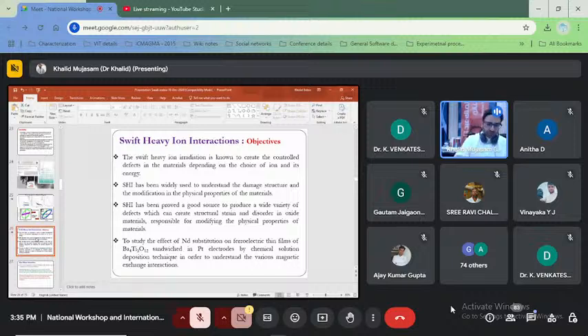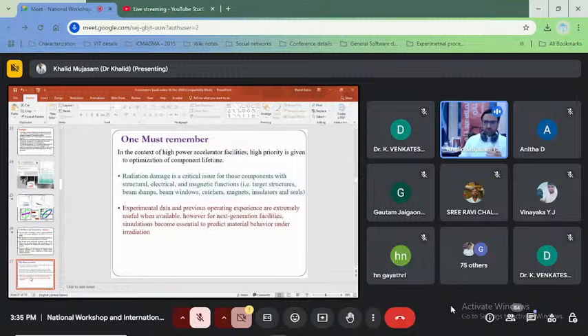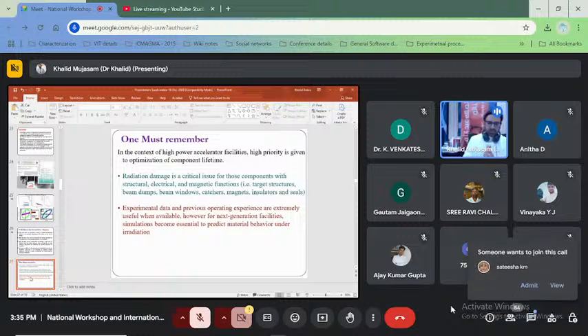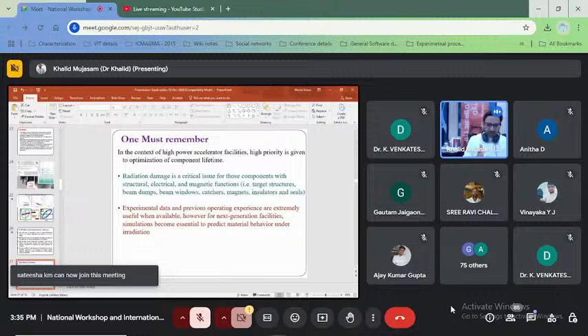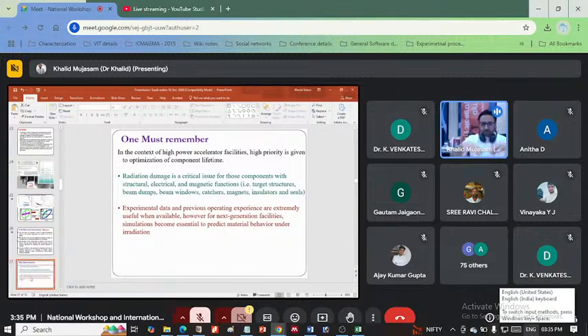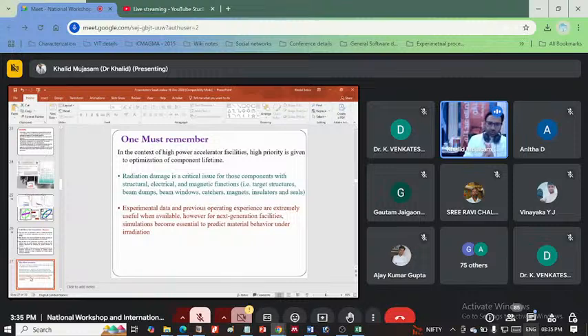That is ion beam implantation. In ion beam implantation, one has to think about how to use the radiation, because the radiation is going to create damages. The damage can have a localized effect, a columnar effect, or multiple defects. You have to determine what energy range you are going to pick, what the stopping energy range is, because once an ion impinges on your material, it can pass through, be absorbed, remain inside, be retracted back, or come close, pass on some energy, and then reflect back.